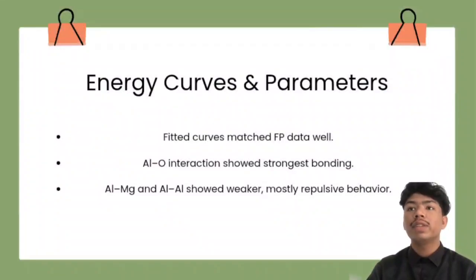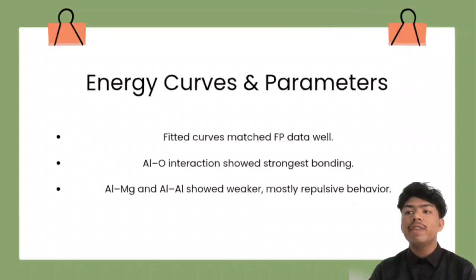The first result from this study involves validating the accuracy of the fitted interatomic potentials. Figure 1 compares the first-principles DFT data with the fitted energy curves for 3 atomic interactions: aluminum-magnesium, aluminum-aluminum, and aluminum-oxygen. For aluminum-magnesium and aluminum-aluminum, the fitted Buckingham potential curve closely matches the DFT reference, capturing the correct repulsive behavior at short distance and decay at longer range. For aluminum-oxygen, the Morse potential was used, as these interactions are strongest and partially ionic. The Morse fit accurately followed the deepest energy well of the DFT curve, indicating the strongest bonding. The successful fitting validates that the chosen potentials replicate real atomic behavior accurately. These validated parameters are then used in all subsequent molecular dynamics simulations.